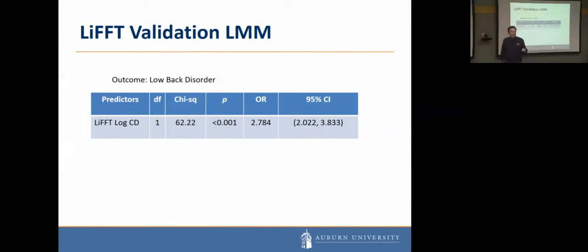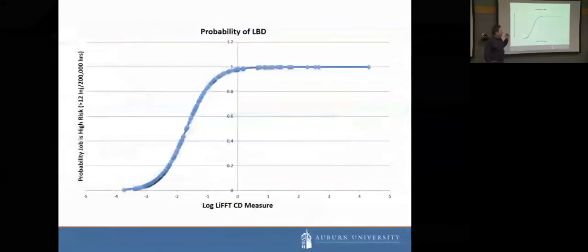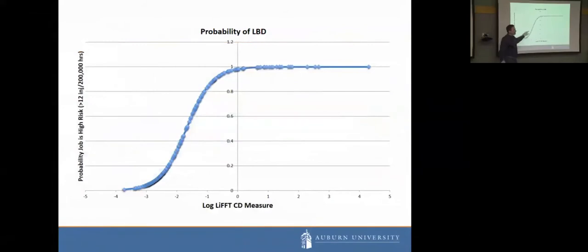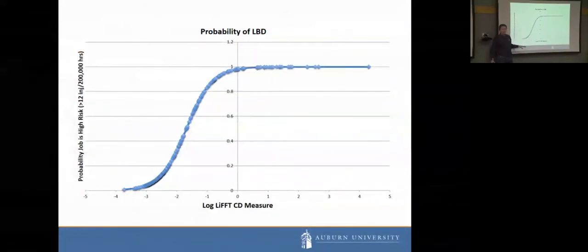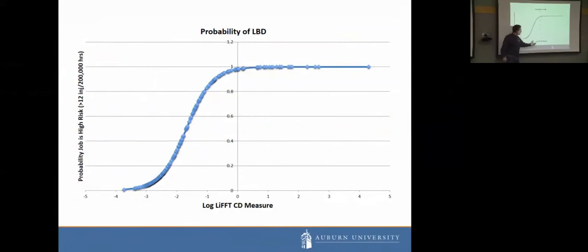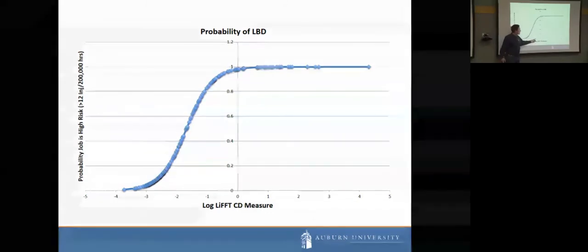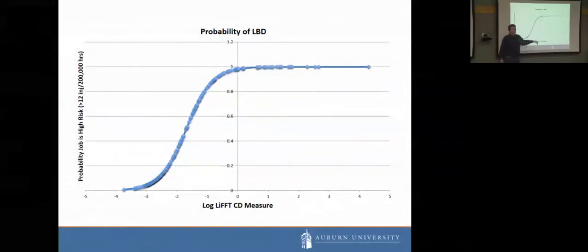We're using the log of the cumulative damage measure that we calculate. That means that for every increase in magnitude, there would be a 2.78 times increase in risk. And this is what the relationship looks like when you plot it out. This is what the logistic regression plots out. So this is our log LiFFT cumulative damage measure. And as it increases, you see a strong increase in the risk of low back disorders.